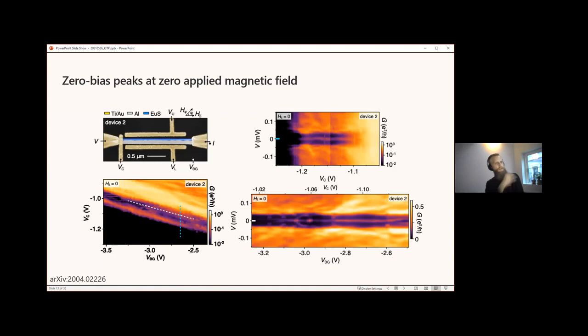So essentially, for this gap of 50 microelectron volts or so, and the same thickness of aluminum, at zero applied magnetic field, we expect to have a superconducting gap of around 230 microelectron volts. And here we have 50 microelectron volts. And it really depends if you assume this is a topological phase or not. So basically, it's either 180 microelectron volts difference between the gaps or 280 microelectron volts.